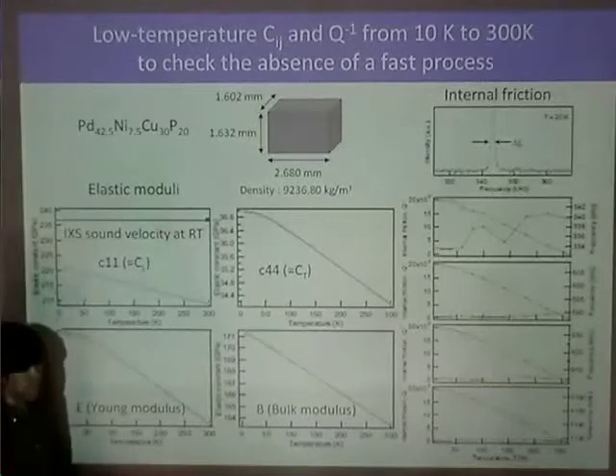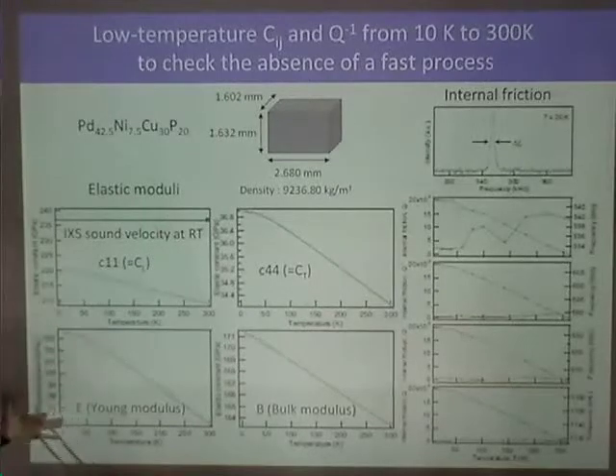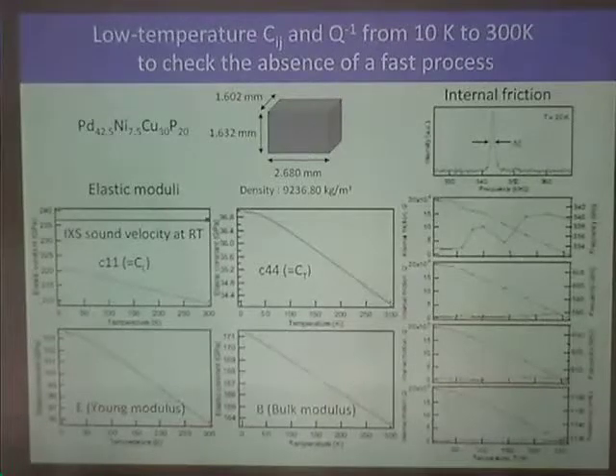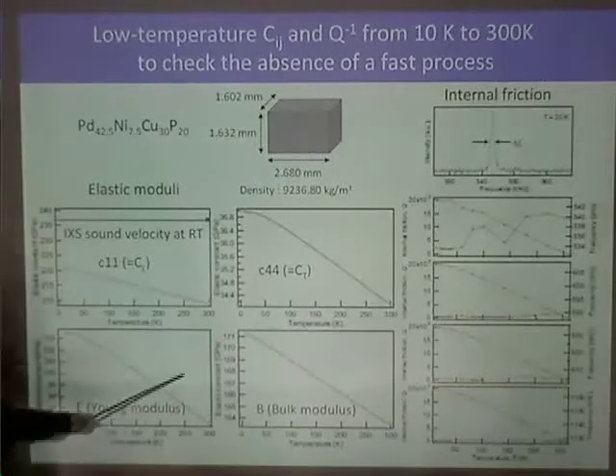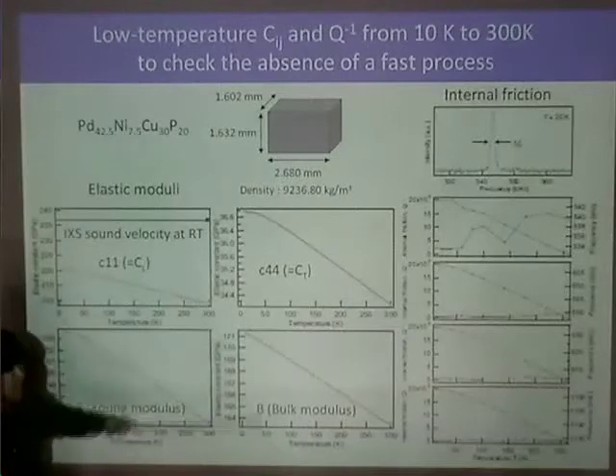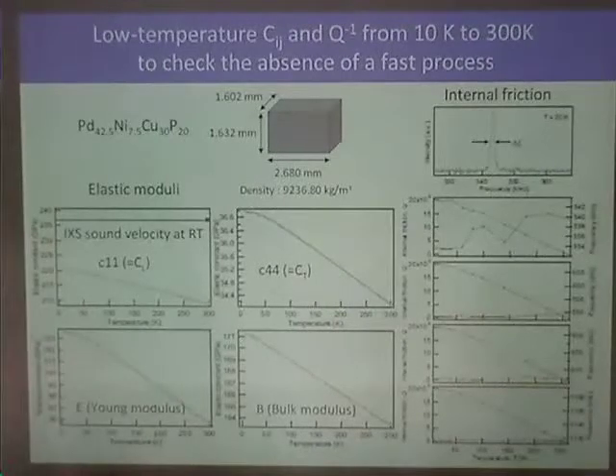How about a quantum process? So for example, mu relaxation or fast beta. A fast process may be activated quantum mechanically at low temperature. At lower temperature, this flattening may be a quantum phenomenon rather than a classical phenomenon. At 10 Kelvin, two-level systems.